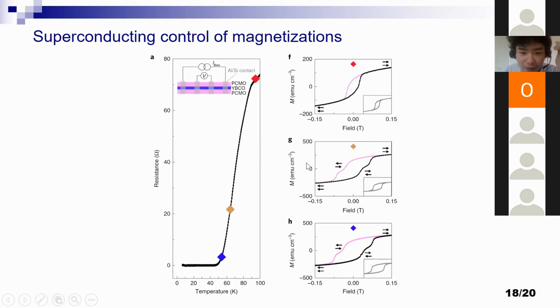And this coupling is quite strong, so we can also observe the opposite effect. So we measured MH of this device with several different temperatures. And basically, two PCMO layers show similar magnetic properties. And above TC, it behaves like a single ferromagnet. This is MH curve. But if you decrease the temperature and go below the TC of YBCO, we can start to see independent switching of two PCMO layers.